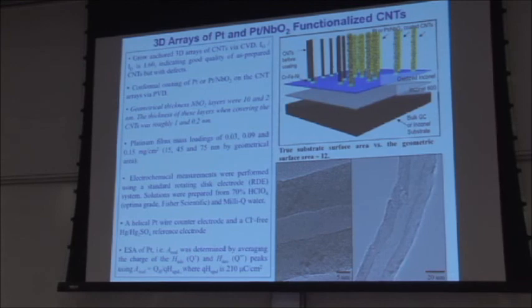And what we did is we grew, and to us this was to some extent a potentially commercializable method, because you could actually use decal transfer to take this architecture and put it in a real MEA. But also, it's kind of a general methodology for working with a variety of carbon-based materials. So carbon microspheres, various graphitic structures, micro rods, et cetera, microcones, nanocones. So what we did is we grew carbon nanotubes in a fairly coarse array on an Inconel support, really an Inconel thin film that was then either deposited on more Inconel or on bulk glassy carbon. And we either just, fairly routinely, sputter deposited platinum on top of it, or we introduced a very thin layer of niobium oxide in between them. So niobium dioxide in between the platinum and the carbon nanotubes.